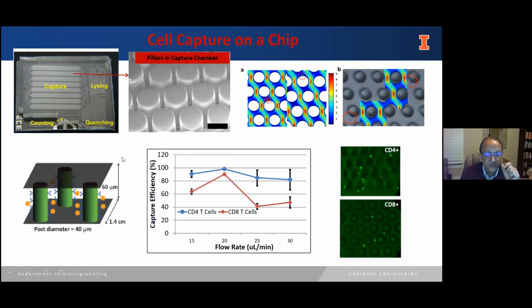The cells are captured in a region with a high surface area to volume ratio. Essentially, these are pillars that we fabricate in PDMS, about 60 microns high and about 40 micron diameter. We attach antibodies to these surfaces, and we can get cell capture as cells flow through this. We've done a lot of modeling to try to model where the shear stresses are highest versus the lowest.